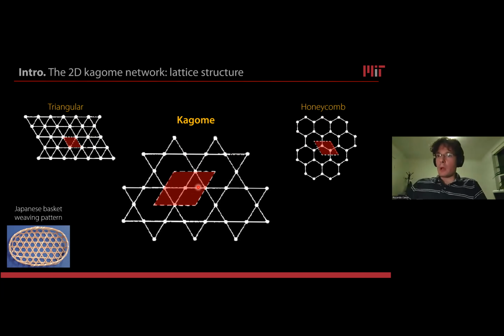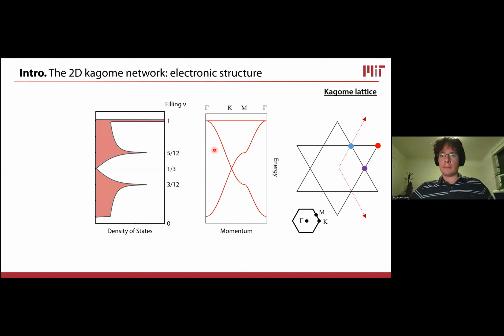So in a way, we can think of the Kagome lattice as a system which can realize some of the physics of honeycomb systems like graphene, but potentially even richer because it can host multiple bands in addition to the ones of graphene. And this is very powerfully shown by even a simple tight binding calculation of what the bands of the Kagome lattice look like. If you neglect this flat band at the top, which is important, and I'll come back to that in a second, and look at the rest, you have these 2 bands which are the same that you would find in graphene under the same conditions for the calculation, so assuming only nearest neighbor hopping.